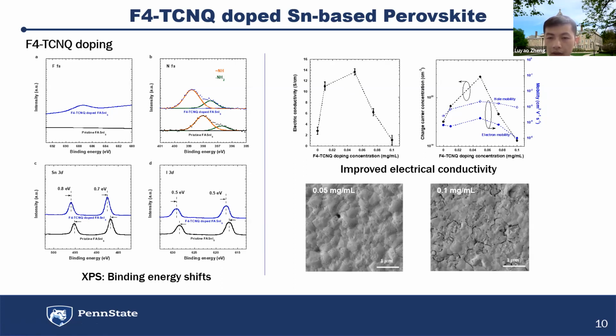But for the higher doping level, the higher concentration of F4-TCNQ, there is a rapid drop of the electric conductivity. This is probably due to the excess of F4-TCNQ inside the material, so there will be some cracks and some phase separation of the thin film, which we can see from the SEM. So we want to maintain the dopant concentration of F4-TCNQ around 0.05 milligram per milliliter. This is the optimized concentration we will use.